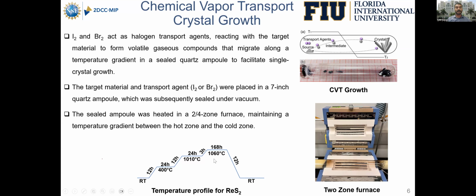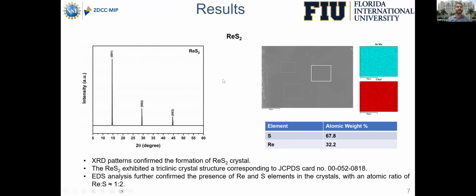As you can see for the temperature profile of RES2, the cold and the hot zone are at 1010 and 1060. So far I have discussed the sealing station and the different methods I have learned to grow the bulk crystals. Moving forward, I'll show you the results. First I'll go with the RES2. You can see from the XRD and the EDS, the XRD pattern confirms the formation of RES2 with this JCPDS card number. And from the EDS, the RE and S are homogeneously distributed all over the surface. Along with that, the atomic ratio of RE and S is 1:2, which is desired.